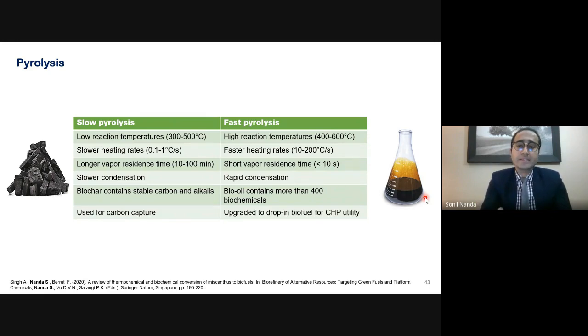So as the biomass undergoes thermal cracking in pyrolysis, it liberates some volatile vapor. If those volatile vapors are kept for a longer duration to slowly cook, it results in the formation of biochar and reduces the yield of bio oil. But if these volatile vapors are released and immediately pushed into a condenser or a chiller, they will start to condense and produce condensable liquids, or the bio oil, which is the case in fast pyrolysis.